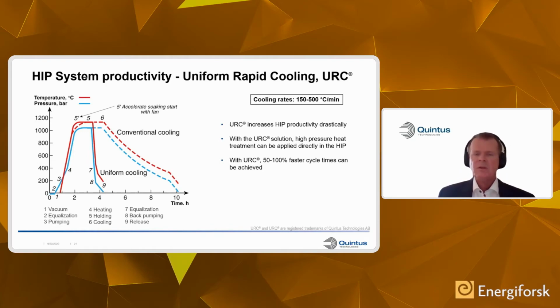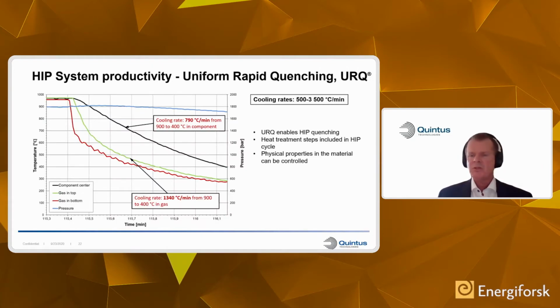If you have products that need quenching or considerably higher cooling rates, we have the Uniform Rapid Quenching, which can reach up to 3,500 C per minute gas temperature. The difference between the URC and the URQ is very similar to quenching. Once the quench cycle has started, it will quench down to the set temperature. If you need a controlled cooling, the URC would be the choice.